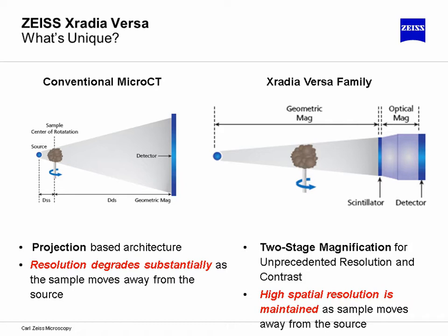So looking at the geometry a bit more of the technique, I showed this graphic on the right-hand side a few slides ago. And now, by incorporating this optical magnification, we've developed a system which was inspired by many synchrotron-based approaches to move beyond conventional micro-CT, which conventionally utilizes a single flat-panel detector and relies heavily on geometric magnification, which places many constraints on the performance of the source, stability, and most importantly, the sample dimension.